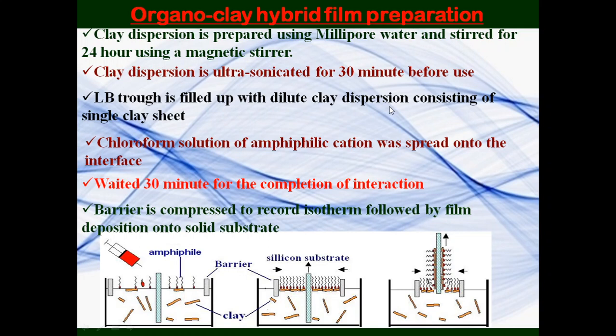The LB trough is filled up with dilute clay dispersion consisting of single clay sheets. Chloroform solution of amphiphilic cation was spread onto the surface. When this clay dispersion water surface is filled up in the LB trough, the preformed oppositely charged, cationic amphiphilic molecule forms a monolayer. Then due to electrostatic interaction, these nanoclay particles are adsorbed onto this preformed monolayer, and thus a hybrid monolayer is formed. A clay dispersed or clay tagged hybrid monolayer is formed, and then using the conventional technique, this can be transferred onto a solid substrate to prepare mono and multilayered hybrid films.